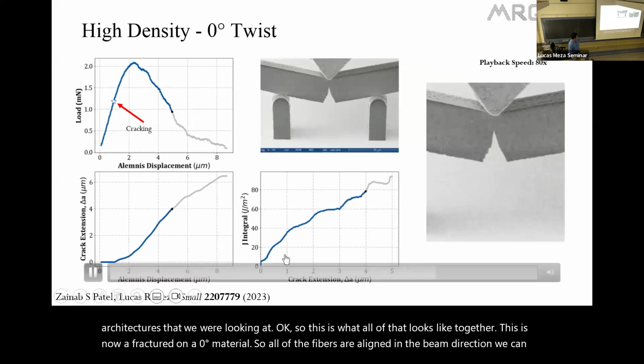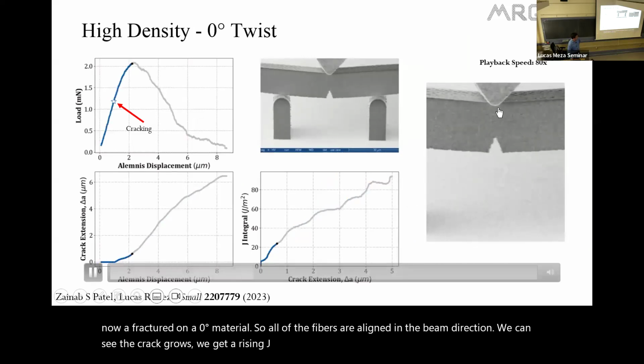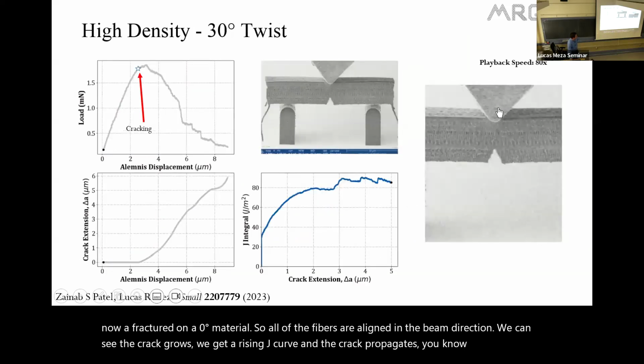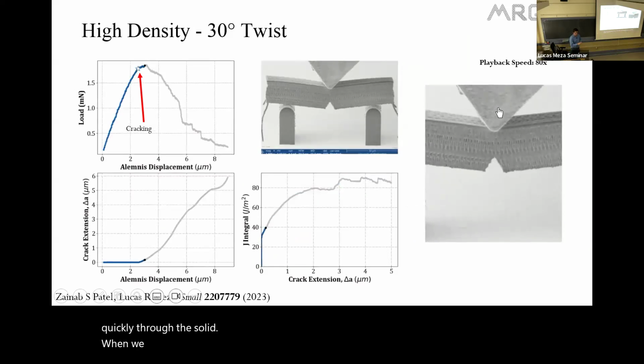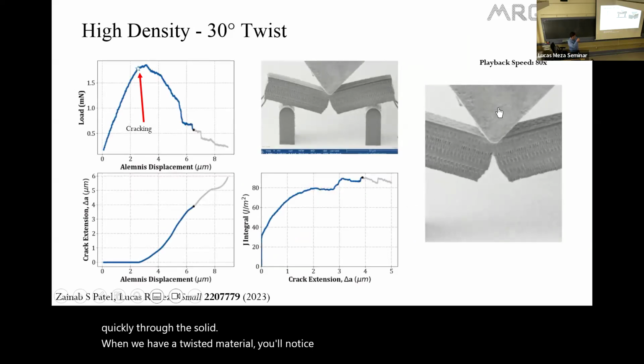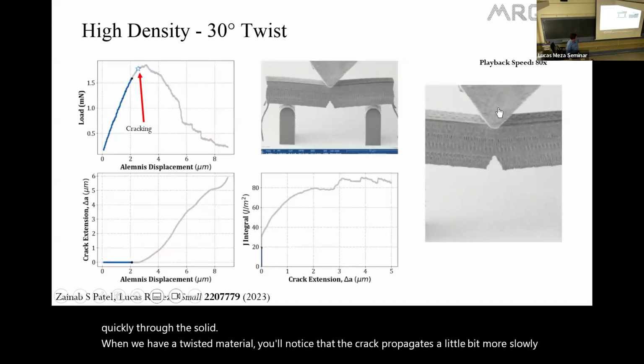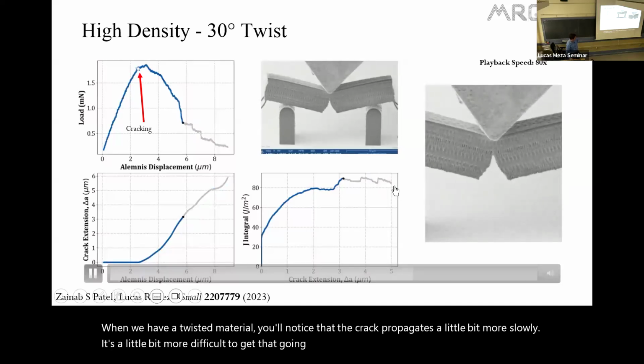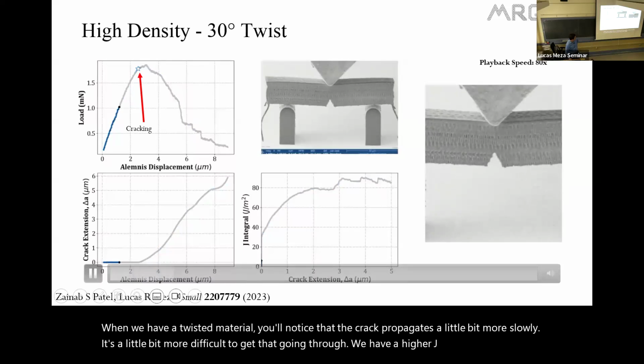We can see the crack grows, we get a rising J curve, and the crack propagates relatively quickly through the solid. When we have a twisted material, you'll notice that the crack propagates a little bit more slowly. It's a little bit more difficult to get that going through. We have a higher J resistance to that crack growth.